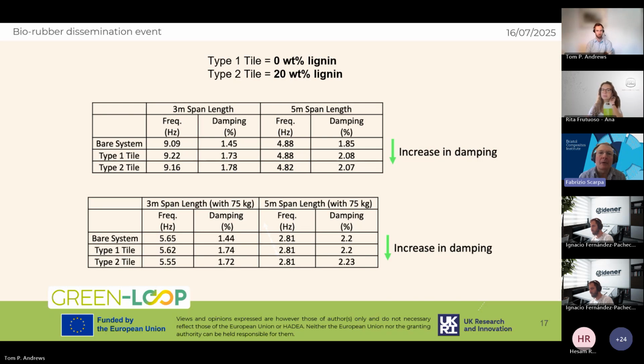Just to give a summary of the results, when you look at those tables, type 1 tile corresponds to the test made with the panels with 0% of lignin, while type 2 are 20% with fractional lignin. As you can see, you have the comparison between the bare system, so we have no panels, and then the presence of the two panels. There is a more significant increase of damping with the presence of the rubber panels, especially when we are looking at the more flexible configuration, so the 5 meters of span length. And if you remember, as Ams talked before, depending very much on the type of application, compliance is one of the strong points of this type of rubber solution.